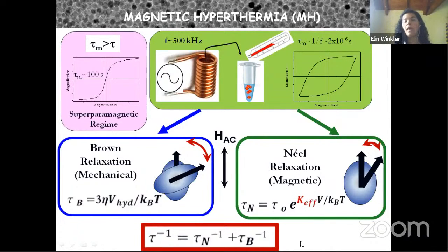And again, as in many phenomena in physics, the real relaxation of the system will be the one with the shorter relaxation time. So, if the Néel relaxation presents a shorter relaxation time, it will be the dominant mechanism, and on the contrary, if this one presents the smaller time, the dominant mechanism will be the Brown relaxation mechanism. And if they are similar, well, it will be a mix of both.